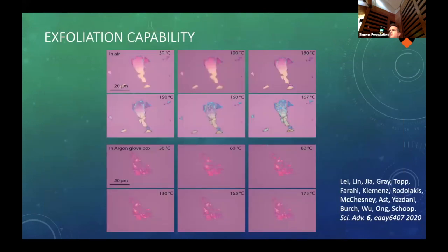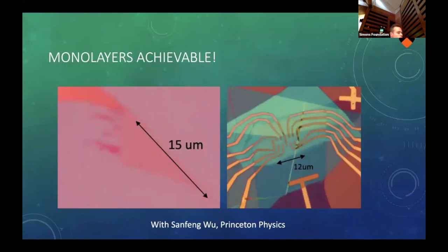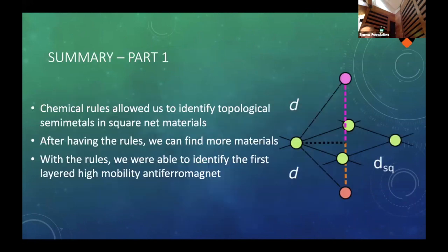Last thing, we also proved that we can exfoliate this material. Let me skip through this. So you can exfoliate this to monolayers and you can try to make contacts. The problem is that these materials are so air sensitive in the monolayer limit that these devices keep dying on us before we get monolayer data. However, I'm optimistic we can improve this in the future.